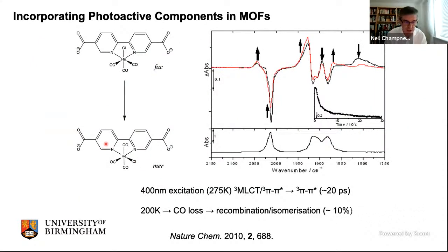So we then look at the photochemistry, and we do this in collaboration with one of my now ex-colleagues at Nottingham, a guy called Mike George. Mike is an expert in time-resolved spectroscopy. What happens here is you shine a light on your compounds, in this case a MOF with a rhenium complex inside, and you excite the rhenium complex and it generates an excited state. You can then follow what happens by infrared spectroscopy of the carbonyl region that you can see here. Essentially it is time-resolved spectroscopy. What you're seeing is peaks disappearing and peaks growing. You can follow this as a function of time, and this tells you whether you're seeing an excited state or not.